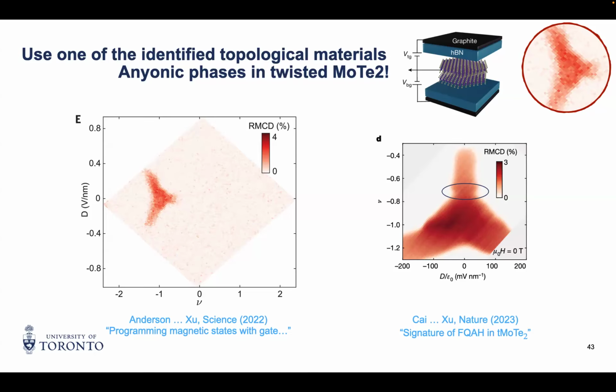So that was the first experiment. Okay, so you see what they do is reflective magnetic circular dichroism, which measures the amount of time reversal symmetry breaking in the system. And so red means that the system is magnetic, and white means there's as many spin up and spin down in the system. Nu is the doping concentration. So they dope holes into the twisted MoTe2 sample. And they can also add the displacement field out of plane that creates an interlayer potential difference. And so they see something that looks ferromagnetic in some part of the phase diagram.